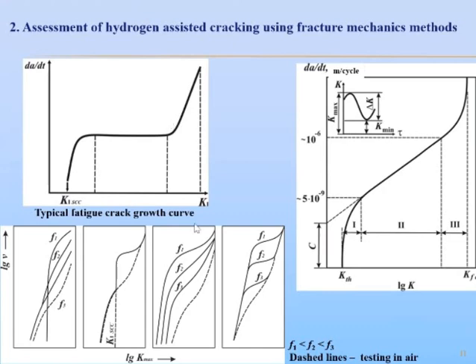And regarding fatigue crack growth rate, corrosive and hydrogenating environments influence the curves, changing them from the typical ones for tests in air in diagrams. They can decrease or increase a fatigue threshold, and the middle part of a diagram may not be influenced or may accelerate fatigue crack growth. If the middle part of the curve is similar to a plateau, it means realization of a stress corrosion cracking mechanism in conditions of fatigue.